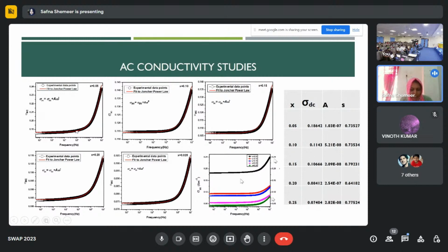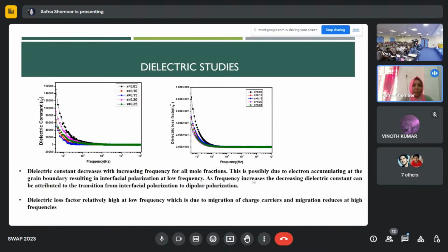And the decrease in conductivity is due to the phase component of MnV2O6, which has higher resistivity compared to vanadium pentoxide. And this is the dielectric of the samples. The dielectric constant decreases with increasing frequency for all mole fractions. And this is possibly due to the electrons accumulating at the grain boundary, resulting in interfacial polarization at low frequency. But as frequency increases, the transition from interfacial polarization to dipolar polarization increases. So the dielectric constant decreases.